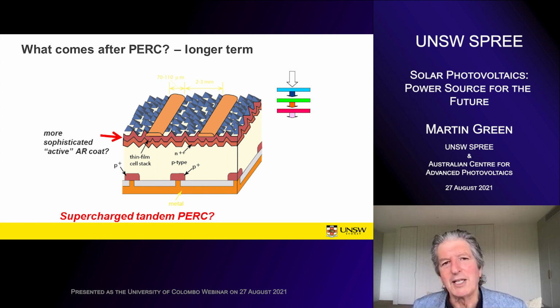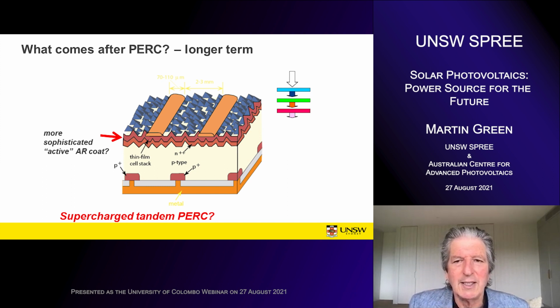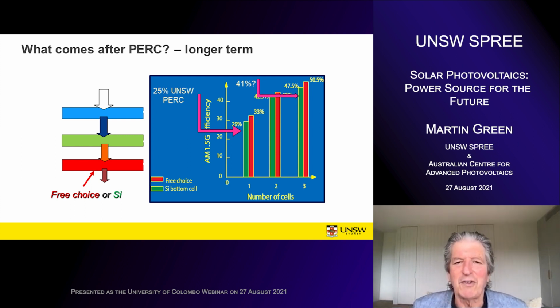So again, you get the photon count. The top cell is limited by the number of photons with that type of energy that are falling on it, and the silicon cell will have fewer photons on it because the top cell's stolen some of them. But because of the higher voltage at the top cell, you end up ahead. So if you do things properly, one cell stacked on silicon can increase the efficiency by about 40%, and 2 cells stacked on silicon can give you close to a 50% boost.